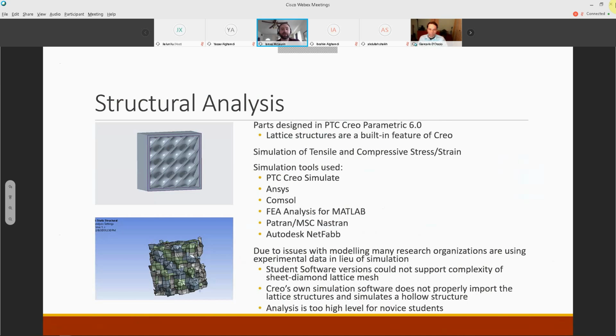Even when you try to transfer the structure from PTC Creo Parametric to simulate, the lattice structure doesn't propagate. So we found a few ways to get around that by transferring it to an STL file, back into a STEP file, and then back into programs like ANSYS. On the bottom left is a mesh that we were able to get out of ANSYS, which is not really defining the shape of what we're looking at, because it's not including all of the empty space between the lattice. That was the best we were able to come up with.